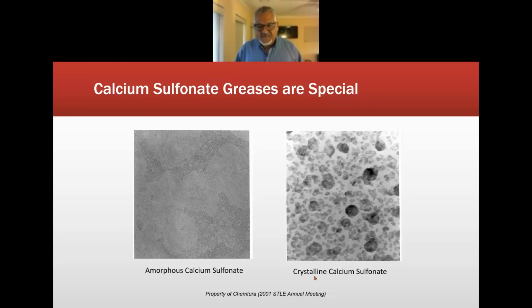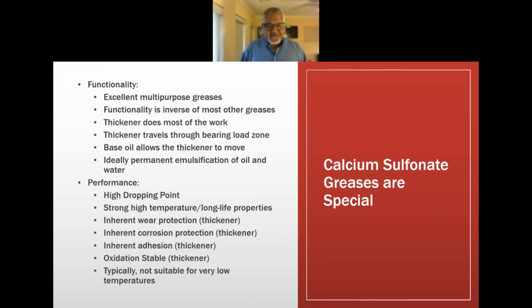But once we crystallize, or you could say complex, a calcium sulfonate grease, you have a crystalline calcium sulfonate structure. What I get out of this picture is that the calcium sulfonate thickener holds onto the base oil very well, and every other liquid that's introduced to it. So why do I call calcium sulfonate greases special? They're excellent multi-purpose greases. It's debatable whether they're good low temperature greases, but I've seen some greases formulated for very good low temperature applications that include calcium sulfonate thickeners.